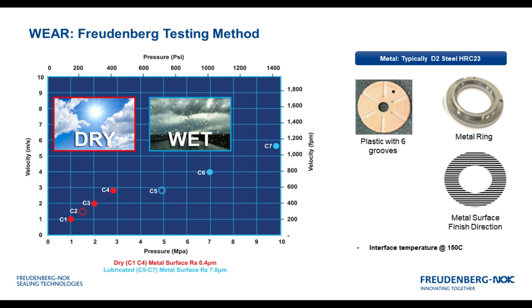The counter surface is a metal counter surface. That can be different hardnesses and different materials. Typically, we'll use a D2 steel at a Rockwell hardness of 23. That is a ring-shaped member that goes against that disc. It is important to note that surface finish is particularly controlled in these tests. We do not use a radial or lathe type record player finish. We use a linear finish.